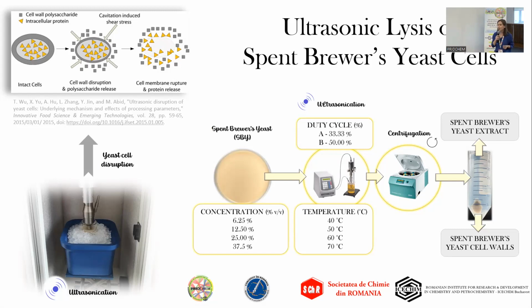So we proceeded to test important ultrasonication parameters to find the optimal yeast cell lysis conditions. We started with testing the influence of sample concentration on lysis efficiency. So of course we prepared spent brewer's yeast samples of different concentrations. We selected the concentration which we considered ideal for lysis, and we proceeded to prepare 2 sets of samples with the optimal concentration using a 33.33% duty cycle for set A of samples and a 50% duty cycle for set B.